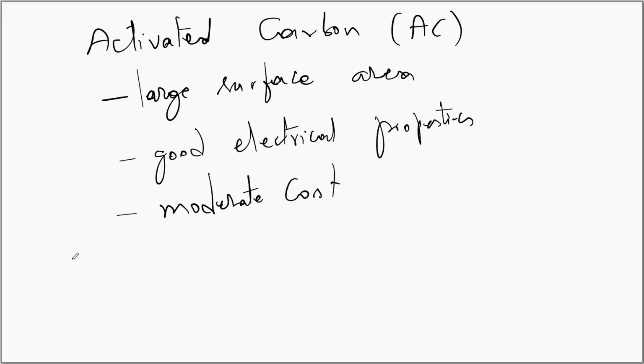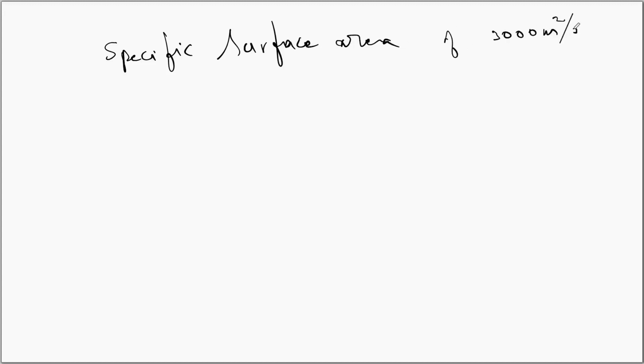Activated carbon is produced using two different mechanisms. The first mechanism is physical activation and the second one is chemical activation. Despite having a large surface area, with a specific surface area of about 3000 meter square per gram, one finds relatively small capacitance when the activated carbons are used as electrodes in supercapacitors.